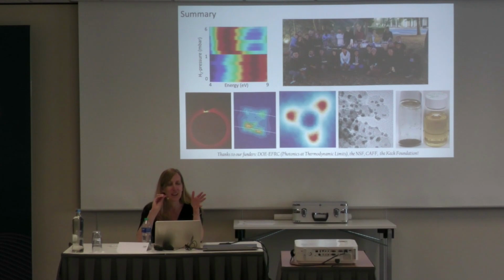The illumination is not necessarily driving local heating of the nanoparticle. The illumination is giving rise to excited electrons in your metal nanoparticle, and those excited electrons are driving the chemistry. I think the field has converged around many experiments showing that it's the hot electrons and hot holes that are driving the chemistry. And now the task ahead is to figure out how to design nanoparticles that get you the highest concentration of hot electrons and hot holes to get the most energy efficient reactions.